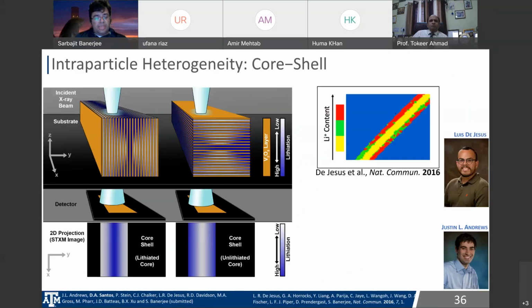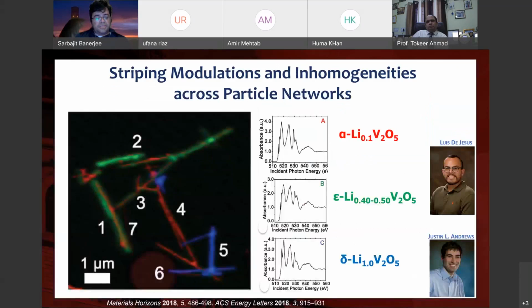Okay. Again, at a single particle level, because of these polaron limitations, you end up getting these lithiation gradients and phase gradients. This is the work of Luis de Jesus and Justin Andrews to image this using X-ray microscopy, and it is typically observed in large particles.